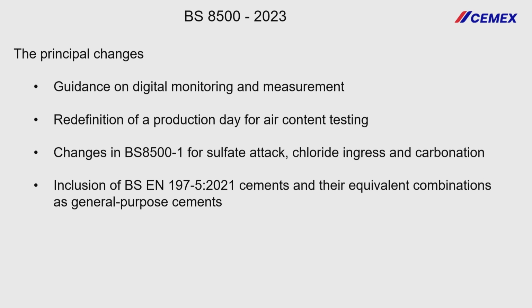A significant amount of concrete is wasted because somebody takes a bucket to do a slump test. You've then got to get rid of that material, and you've then got to wash out your material. So guidance on digital measurement was included in BS 8500 Part 1. Good for me, it redefined the production day for air content testing.